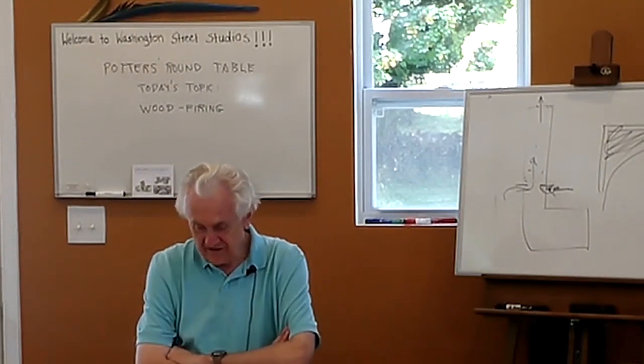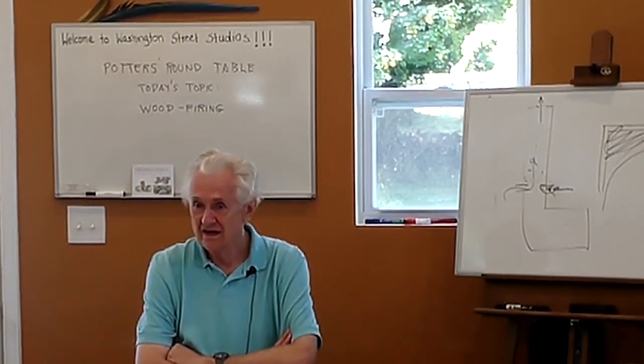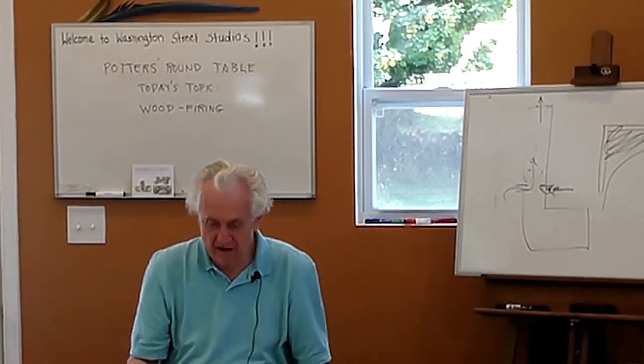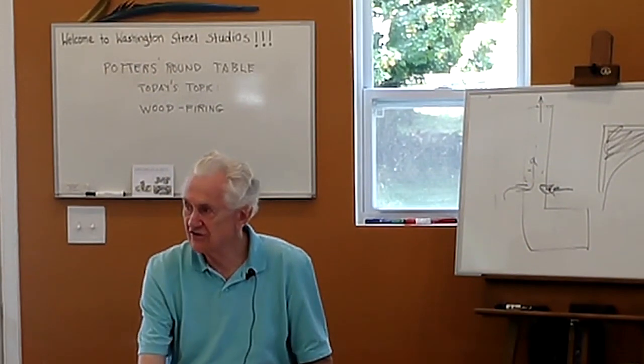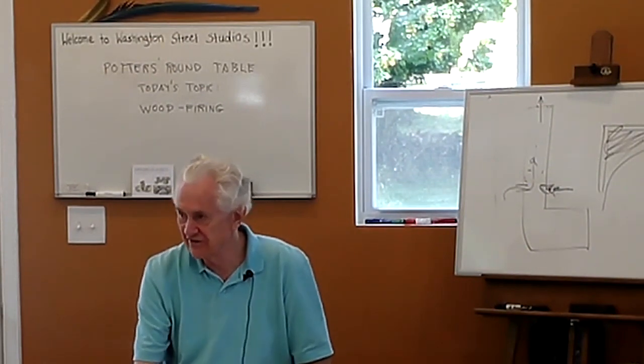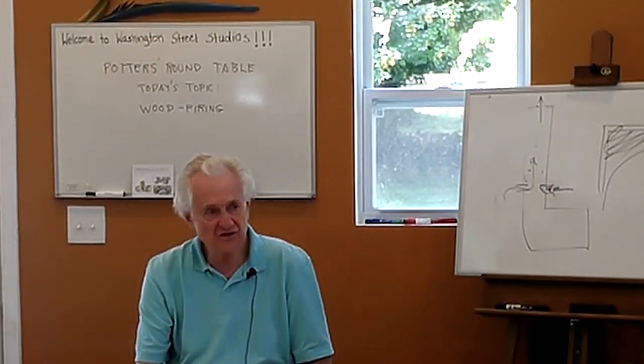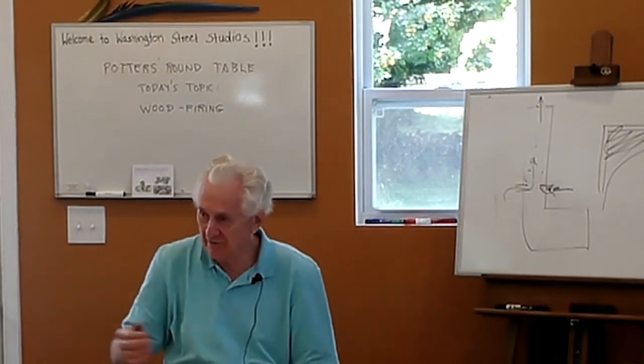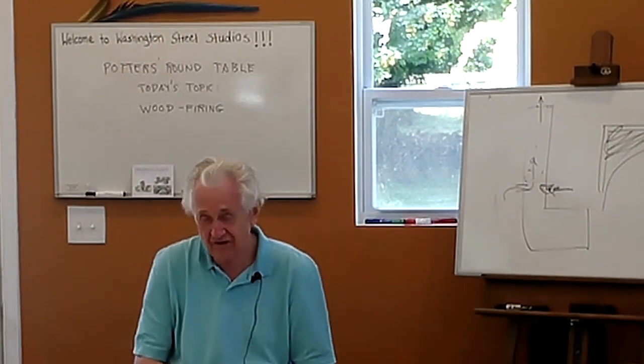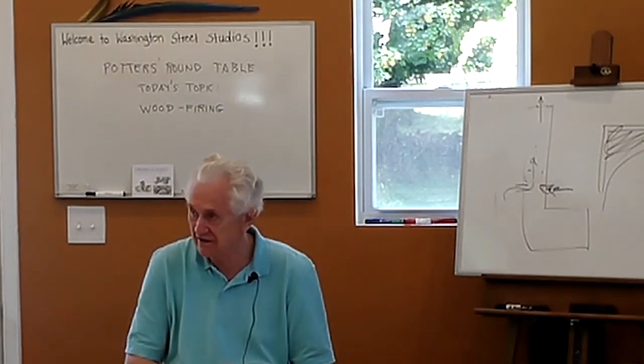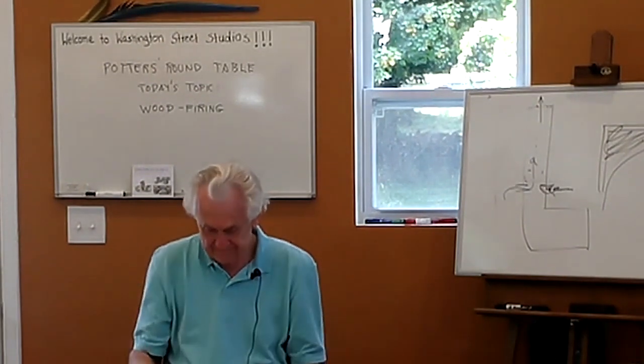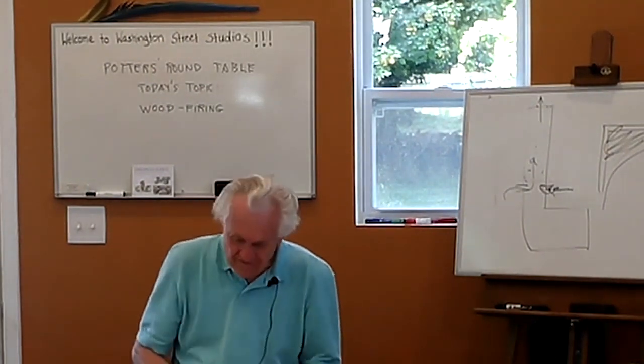And this basically is the choice of the clay. When you're firing with wood, you've got to pick clay bodies because you're never going to fire to just cone 10. So you've got to pick clay bodies that can take much higher temperatures than simply cone 10, because chances are they're going to see temperatures higher than cone 10. And if not, they're going to slump.